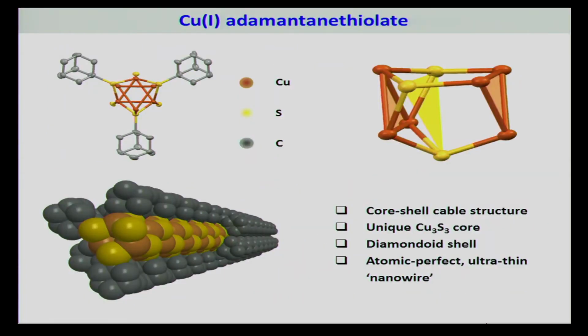So let us take a closer look at one of the examples. This is the copper adamantane thiolate, that is a copper sulfide in the center with adamantane surrounding it. What we have here is really a molecular wire, as we call it. What you have is a cable-like structure with a copper sulfide that is 3 copper, 3 sulfur, and stacking together in the core, forming this long chain of copper sulfide.